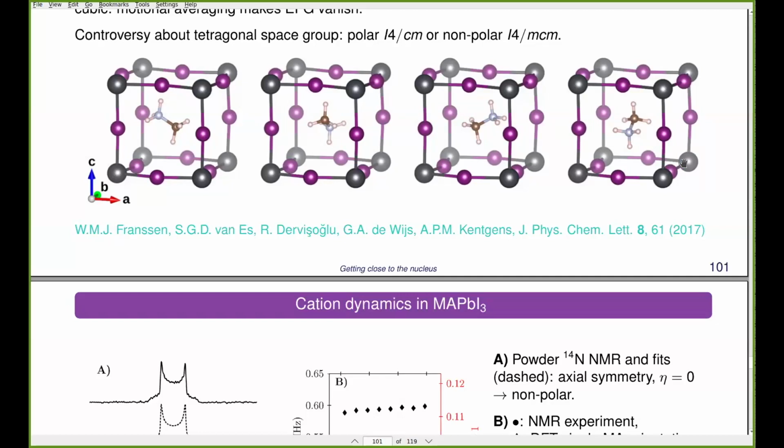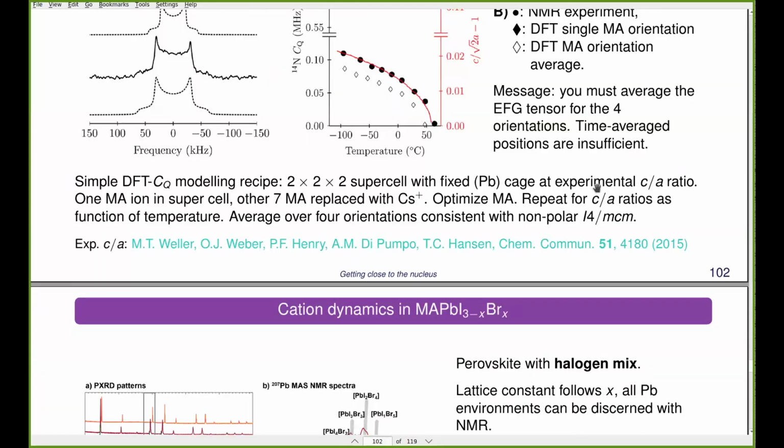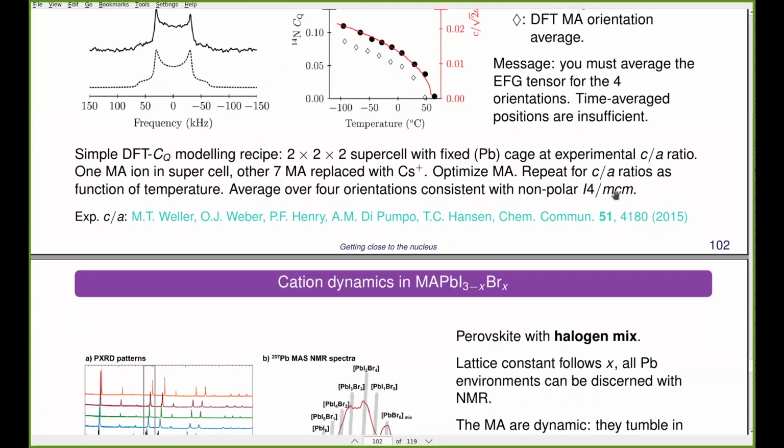So then we want to do an MD, and we do a molecular dynamics simulation where this thing is actually moving inside the cage. But it has to flip very often. It has to sample all the configurations, and this is on the order of picoseconds. So you need a very long one. You need 100, you need 1,000, whatever picoseconds to get this right. You need even more.